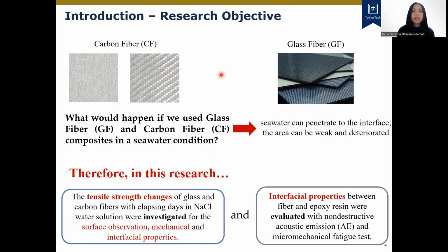we have a question: what will happen if we use glass fiber and carbon fiber composite in seawater conditions? The hypothesis is that seawater can penetrate to the interface of the fiber or the resin itself, so that area can become weak and deteriorate. Therefore, in this research, the tensile strength change of glass and carbon fiber with elapsing days in sodium chloride solution was investigated to know the surface observation, mechanical, and interfacial properties. And the interfacial properties will also be evaluated using non-destructive tests.